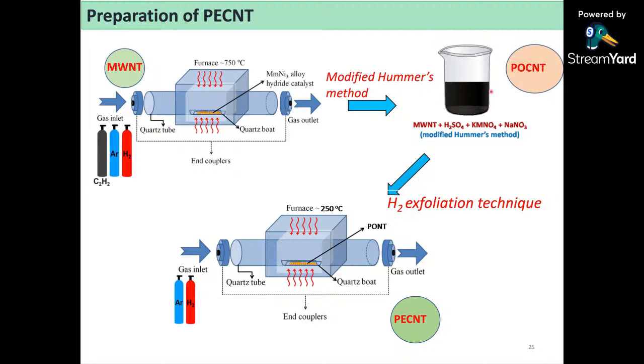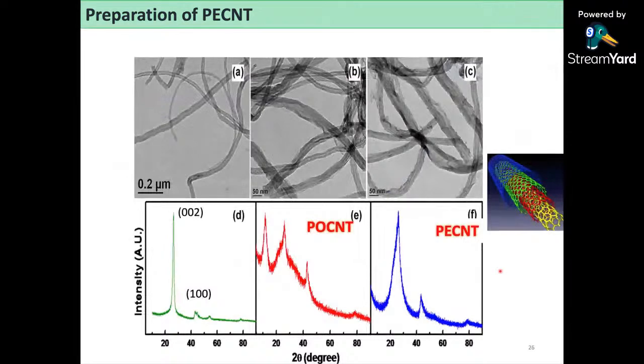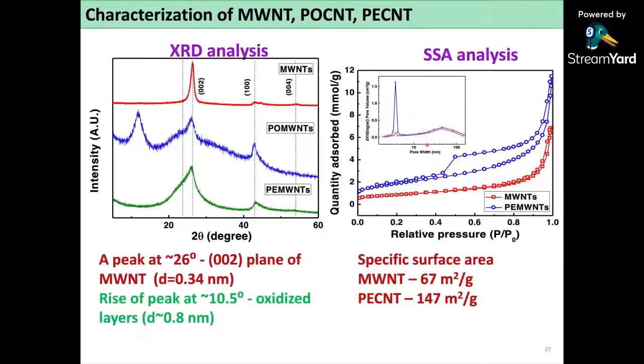So this treatment as well as the exfoliation needs very careful attention in order to get only a few of the layers exfoliated. You can see these are the carbon nanotubes, and you can see that some of the outer layers have been exfoliated nicely in order to get these partially exfoliated carbon nanotubes. And then the BET specific surface area measurements will show almost 140 meters squared per gram, compared to the specific surface area of multi-walled nanotubes, or more or less double.